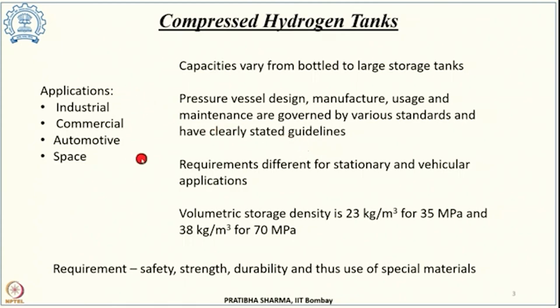Now, if we see these applications, their capacity varies and the requirements from these storage tanks are very different. The difference is drastic when it comes to stationary or vehicular application. The weight and volume is a bigger constraint for vehicular application as against stationary application. We have learnt in the earlier class that as we compress gas to higher pressures, the volumetric energy density increases. The commercially available tanks meant for vehicular application can store hydrogen at 35 MPa or 70 MPa. As against hydrogen under normal temperature and pressure conditions, where the density is 0.08 kg per meter cube, the density increases to 23 kg per meter cube when compressed to 35 MPa, while when it is stored in a 70 MPa tank the density increases to 38 kg per meter cube.